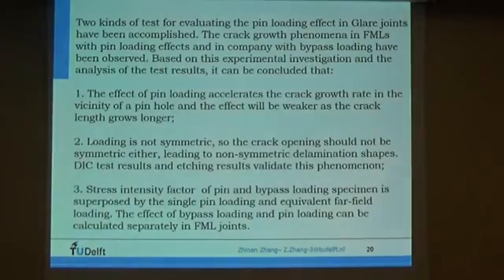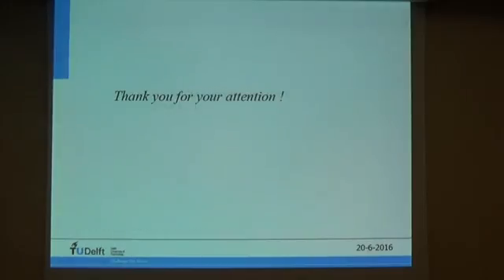Finally, the conclusion. First, the effect of the pin loading accelerates the crack growth rate in the vicinity of the pinhole, and the effect will be weaker as the crack length grows longer. Secondly, the load is not symmetric, so the crack opening should not be symmetric either, leading to a non-symmetric delamination shape. DIC test results and etching results validate this phenomenon. The stress intensity factor of the pin and bypass loading specimen is superposed by the single pin loading and the equivalent far field load. The effect of the bypass load and the pin load can be calculated separately in the fiber metal laminate joint. Thank you for your attention.